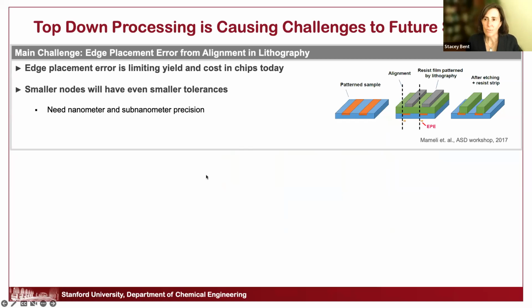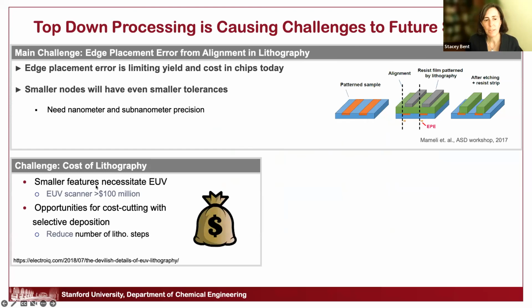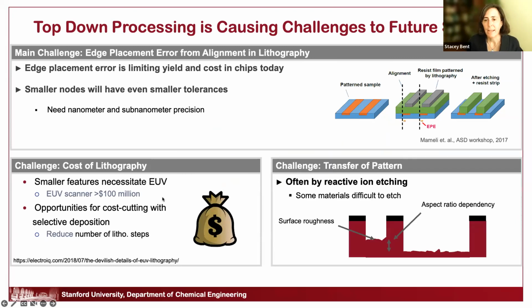This is causing challenges to future scaling. One of the big ones I already mentioned before is edge placement error. So if there's a little bit of an offset, then we can have yield degradation because you have devices that don't work here. And edge placement error is one of the biggest challenges in fabrication today. But there are other challenges too. The cost of doing lithography, especially as we're looking at extreme ultraviolet, is quite high. And then, as I mentioned, the numbers of materials that are being incorporated into modern devices is getting larger. And some of these materials we don't have good etch processes for. So all of the standard fabrication leads to some of these challenges.